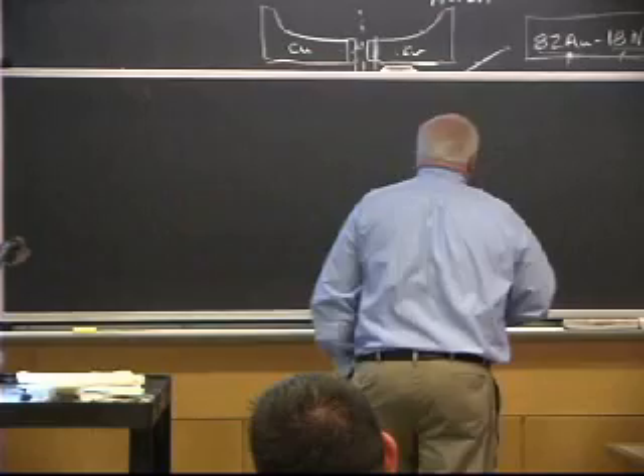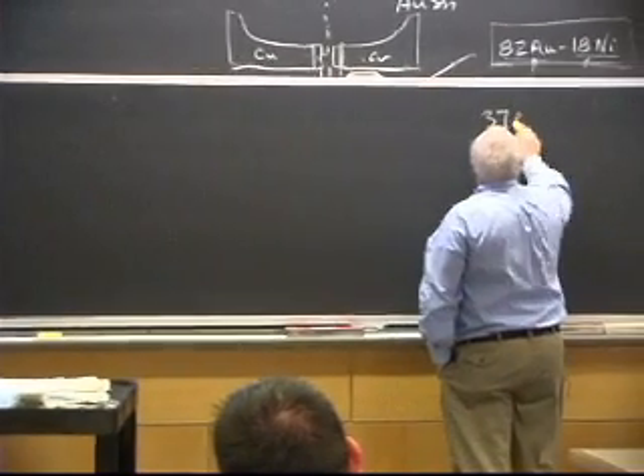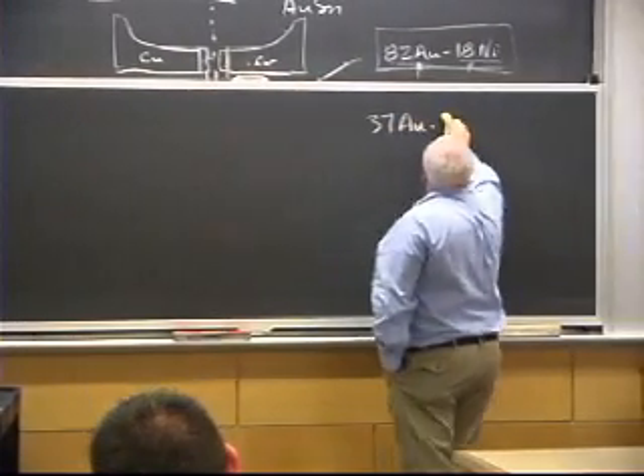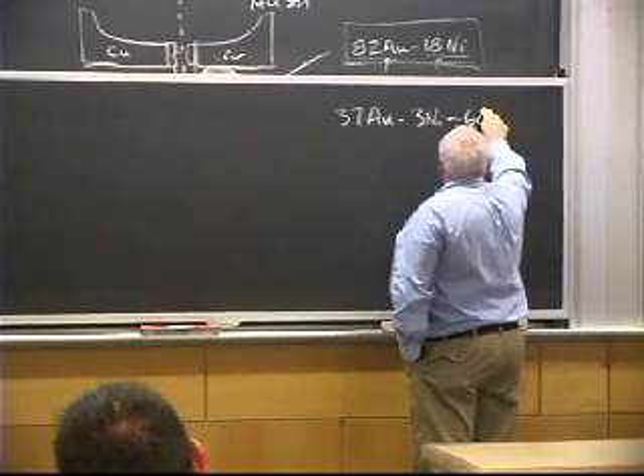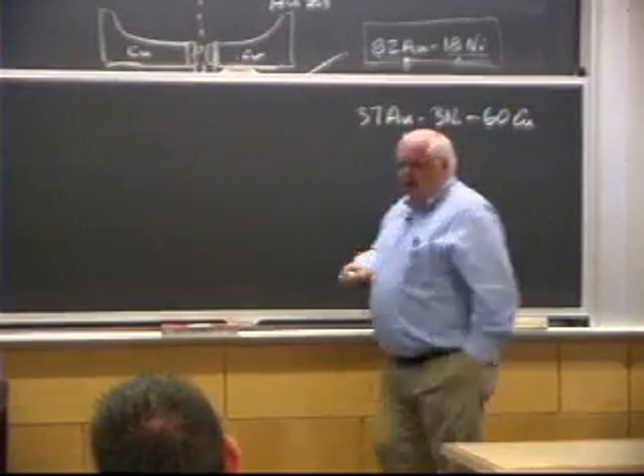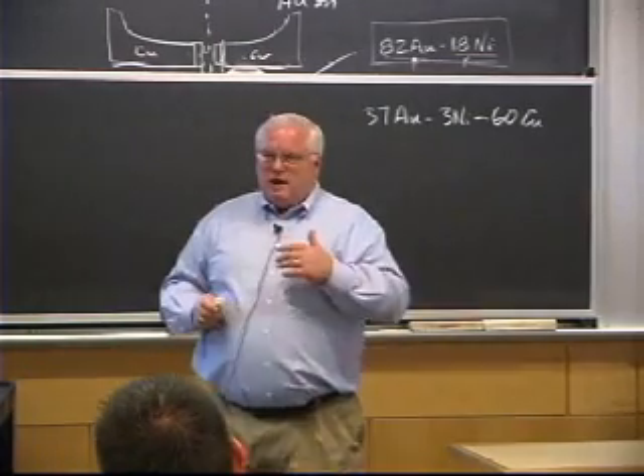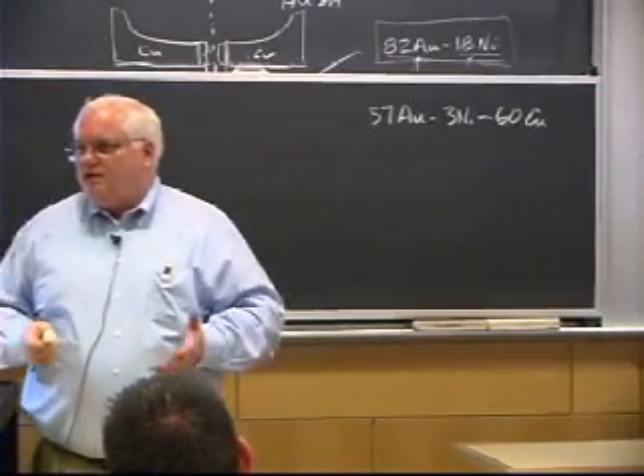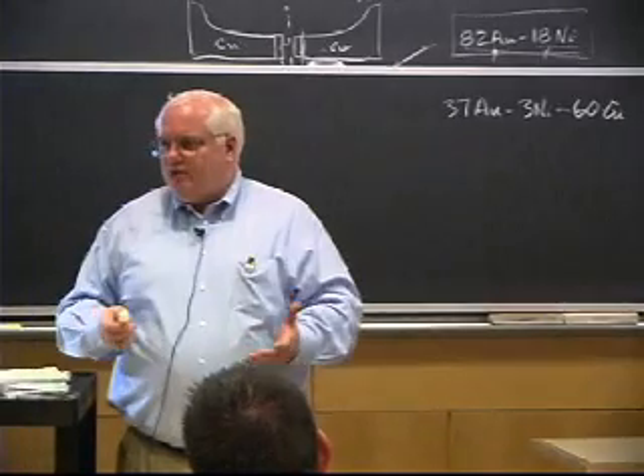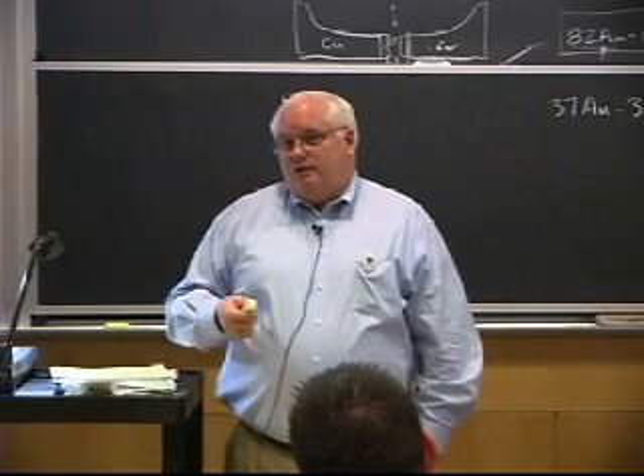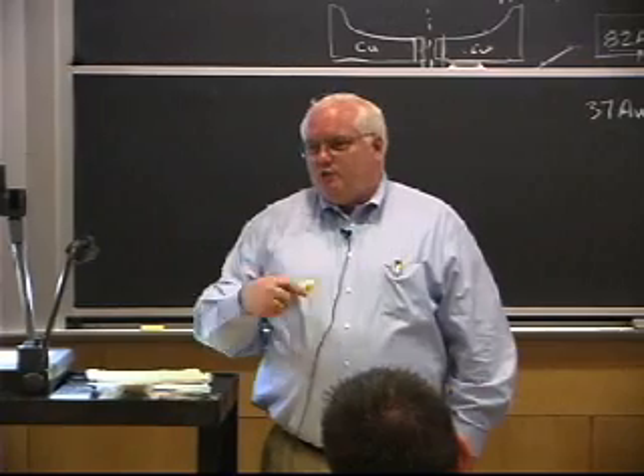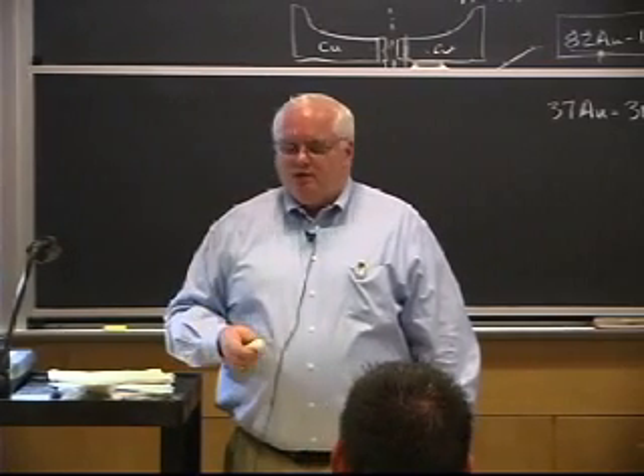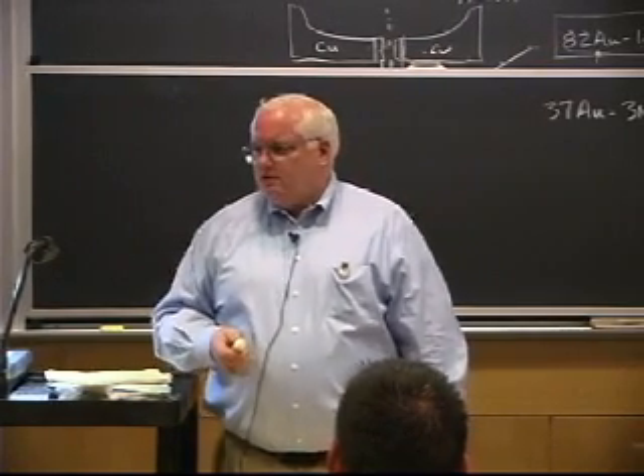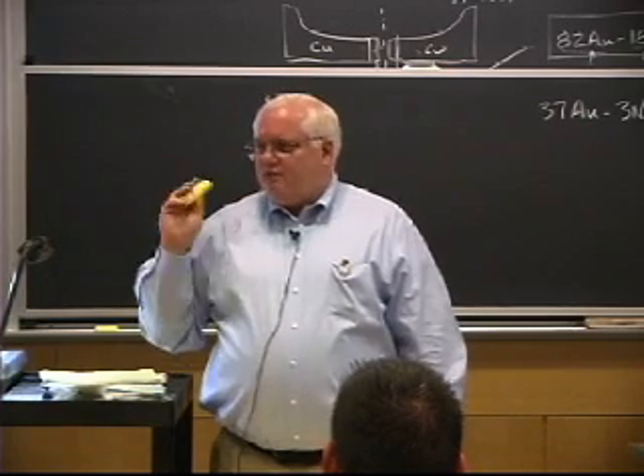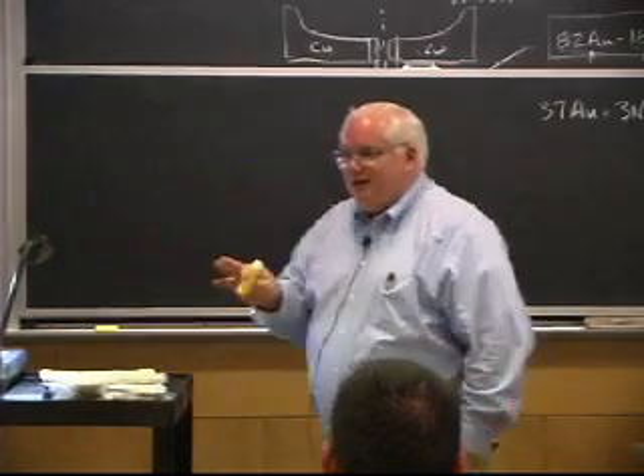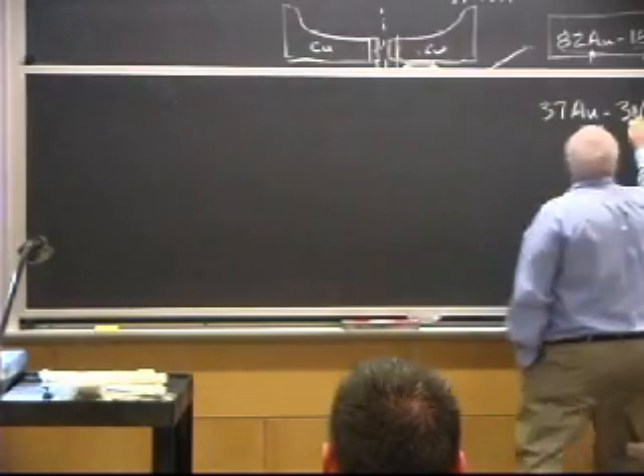They said, we tried a braze alloy, and it turns out it was 37% gold, 3% nickel, and 60% copper. And we got these great properties, and we're trying to sell this to the Navy, but they think we're just trying to lower the cost of the braze alloy. This is such a critical thing that they won't buy off on it. I said, I don't know what you've got, but I'll go look at it. So I gave a sample to my graduate student to do metallography and polish it. He comes back and says, I can't find the braze. I go and look at it, and I realize they had developed a TLP joint. They didn't know it. They thought they were just using a different braze alloy with less nickel.